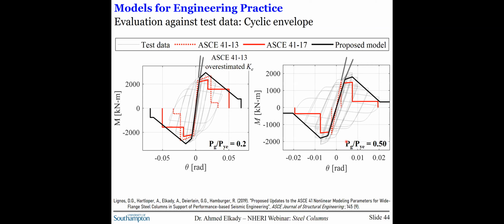And this is due to the fact that the contributions of the shear deformations were not included in the computation of the elastic stiffness. And this contribution can actually be substantial. It can easily reach about 20% in deep columns. And now this issue has been resolved in the current ASCE 41 standard.